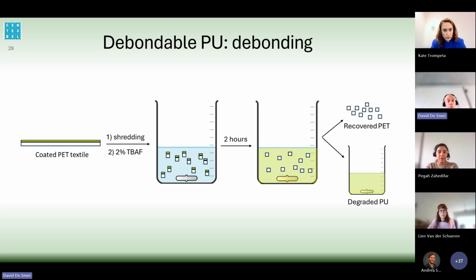So you have your coated polyester textile with a PU coating. You need to shred it into pieces, and then we put it in a 2% solution of tetrabutylammonium fluoride (TBAF). If you let it stir at room temperature for 2 hours, you will see that the coating will be removed from your textile. And by just a simple filtration process, you can separate your recovered polyester textile and your degraded polyurethane, which is still in the solution.